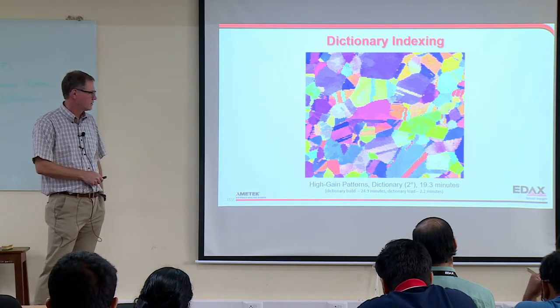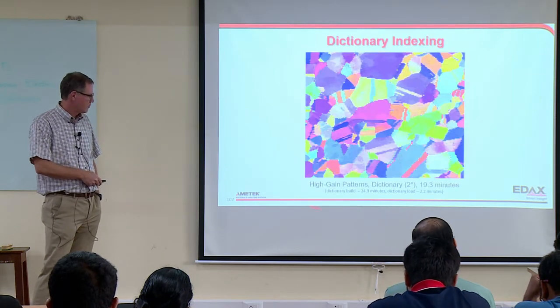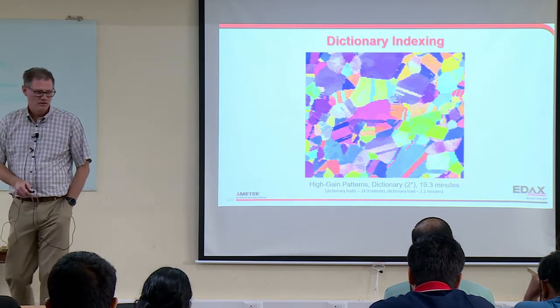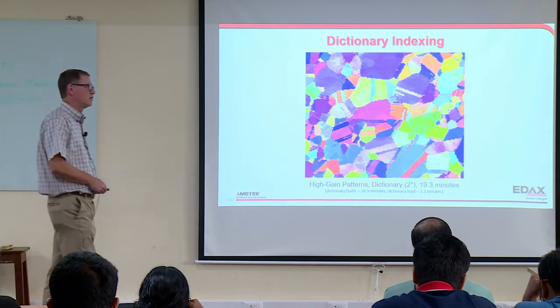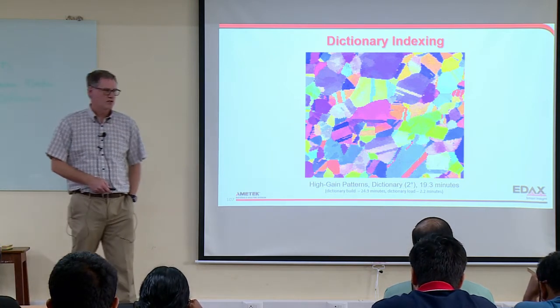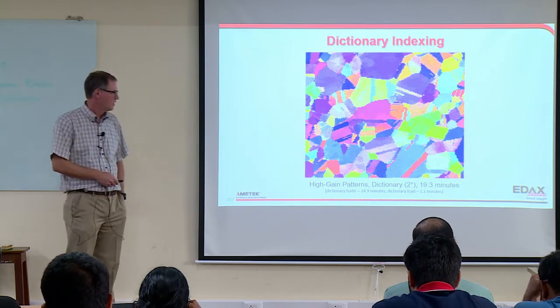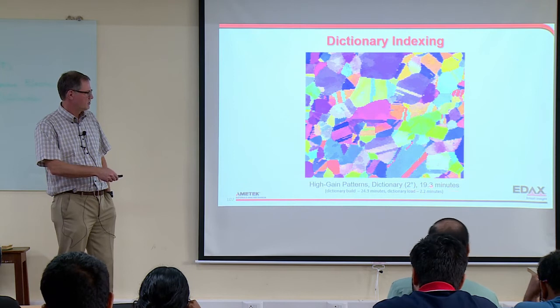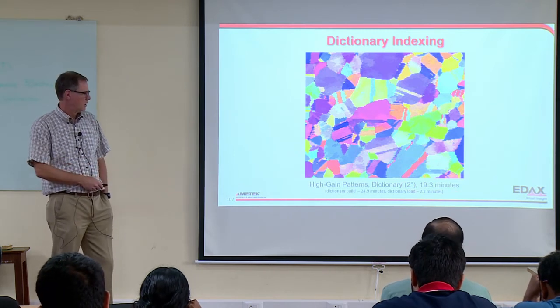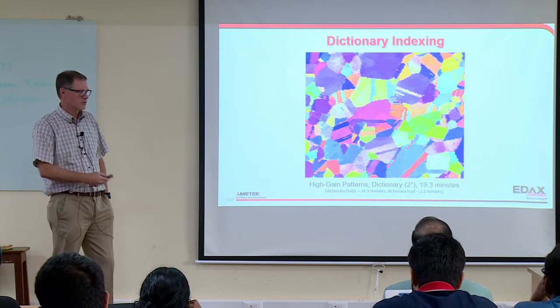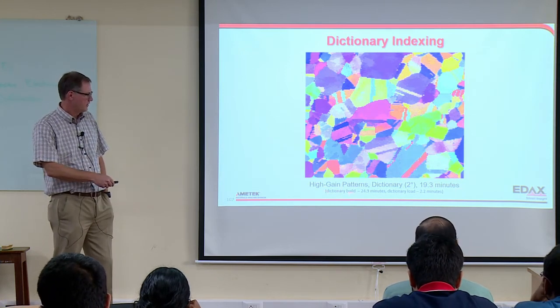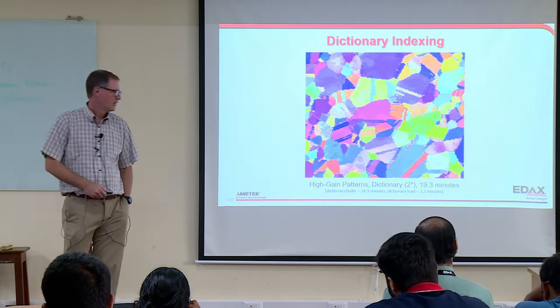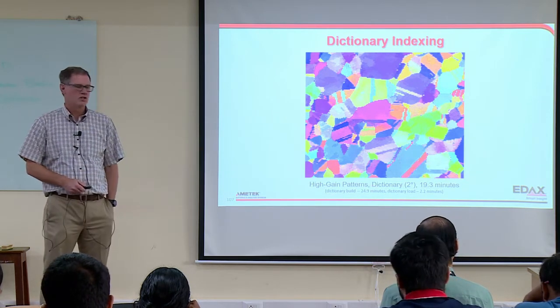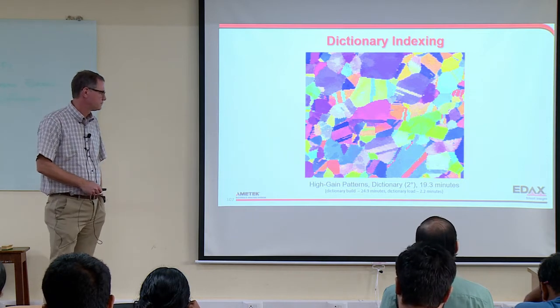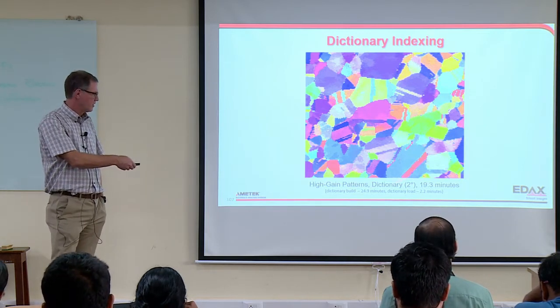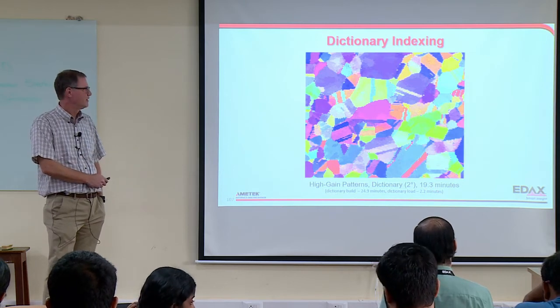It's all really nice. Just to show you, this is on my computer, which is a good computer. Probably about a $6,000 US dollar computer, so it's not super expensive. A dictionary at 2 degrees took 19 minutes to do this. And that's without the GPU, so that's pretty good, it's reasonable. It took me longer to build the dictionary than it did to do the indexing. But once you build a dictionary once, you're pretty much good as long as you're working in the same calibration. Actually, 2 of those 19 minutes was just to load the dictionary into memory.